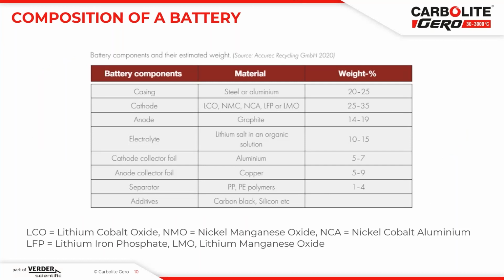So a battery consists of a casing that is steel or aluminum based, then cathode materials, which are LCO, NMC, NCA, LFP, or LMO. Below the table, there is written what it means, like oxide materials. The anode is mainly graphite, but there are also developments in the field of silicon and other materials. The electrolytes are very important for the conductivity in lithium-based batteries. Then anode and cathode materials, aluminum, copper. The separator is the membrane, which is mainly polymers, and additionally some additives, which are carbon black. The weight percentage you have seen on the right side is about 20, 25, 14, 10, 5, 5, and 1% respectively.